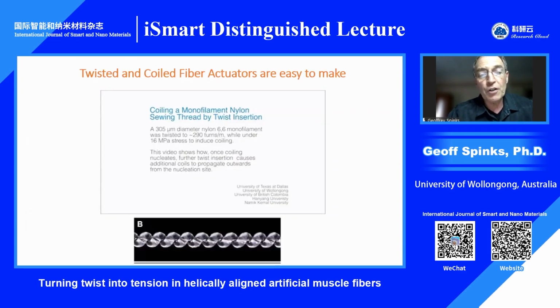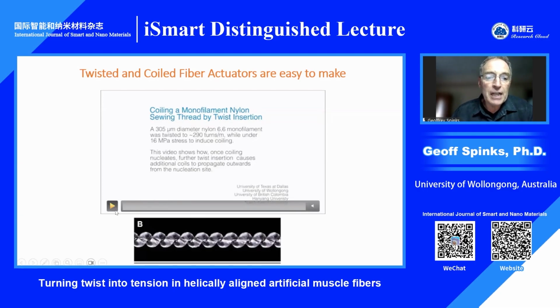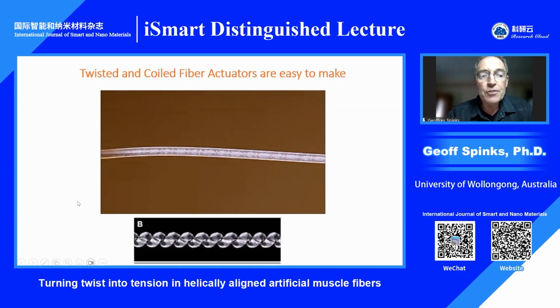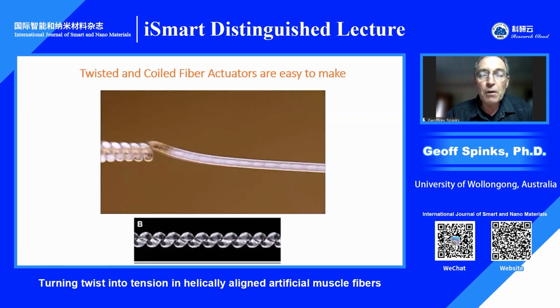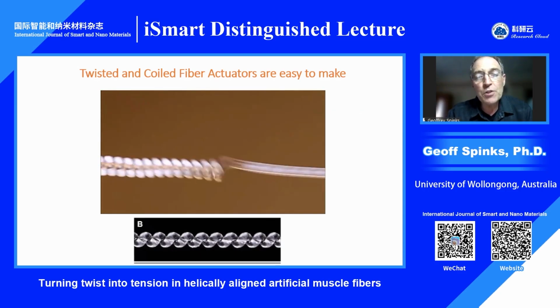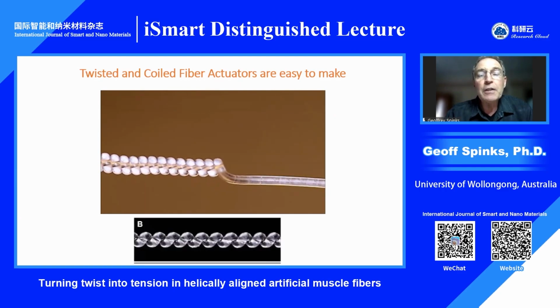Now, one of the really exciting things about these artificial muscles is that they're really easy to make. And pretty much any textile fibre can be made into an artificial muscle just by putting a bit of tension on it and then twisting it. And eventually you can reach the point of over-twisting where these tight coils form. At this point, there's a heat setting process just to lock in that structure. And then that's it. Then you've made an artificial muscle from a cheap material with a really easy process and an artificial muscle that works really well.